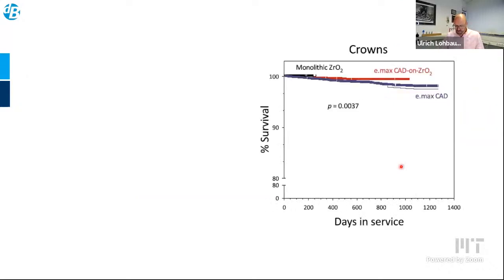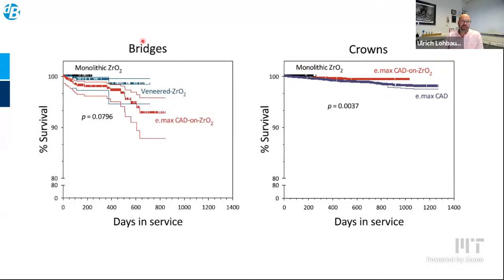We retrieved those 35,000 cases, and we did a Kaplan-Meier survival rate, clinically speaking. So for crowns, we can say, okay, monolithic zirconia is the strongest material, quite clear, and the weakest material has the lowest survival rate over time. If we do this with bridges, which are much more loaded, then we see that those veneered versions are less fracture resistant than the monolithic version of zirconia. The survival rate drops with time.